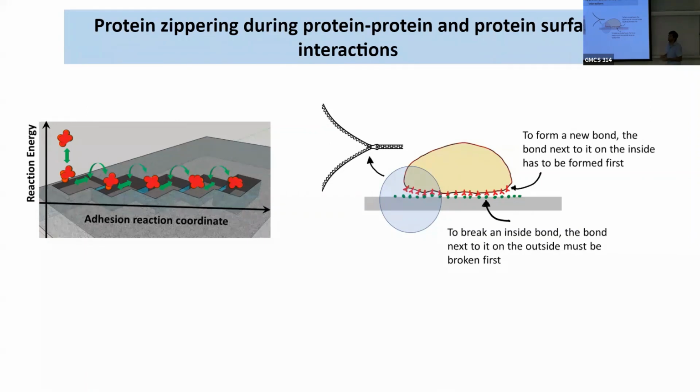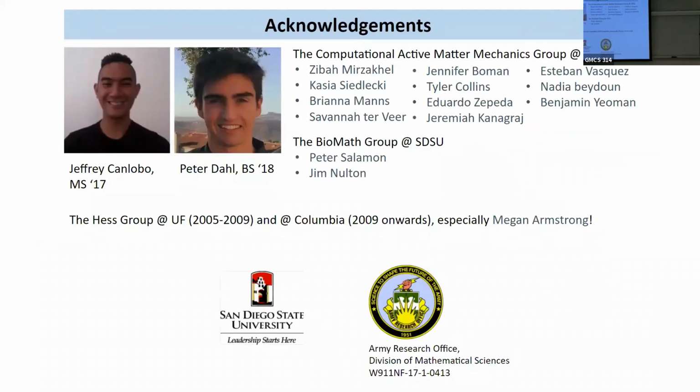Now, what does this mean for other things? Because we were assuming exponential times, that means we were assuming there was one fixed rate for the proteins to get off, right? But there isn't. It's actually a power law distribution. And so that means all the kinetics that we calculate in our pharmacodynamics, pharmacokinetics, or protein-protein interactions will not stay true, because you don't have that one dissociation rate. It's time dependent, in fact. So what does that mean? That's something we're contemplating. But with that, I will end this.